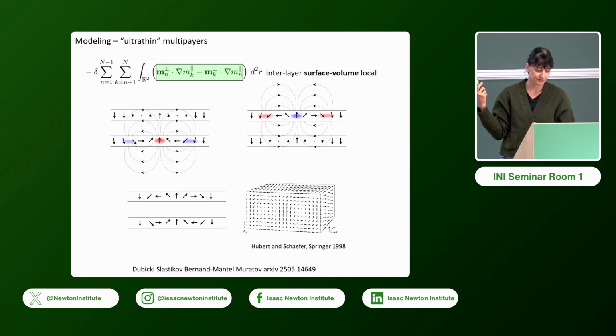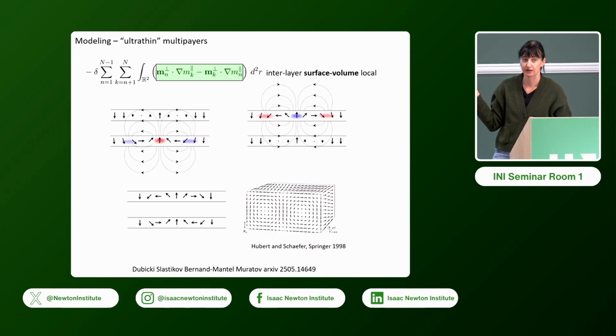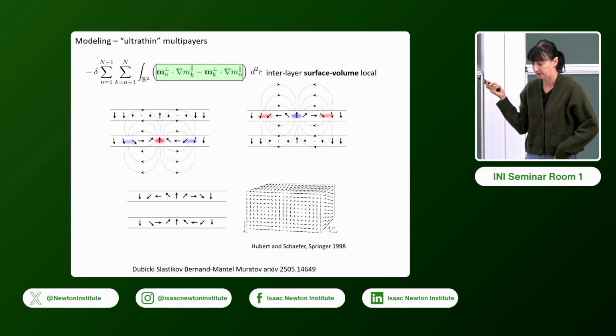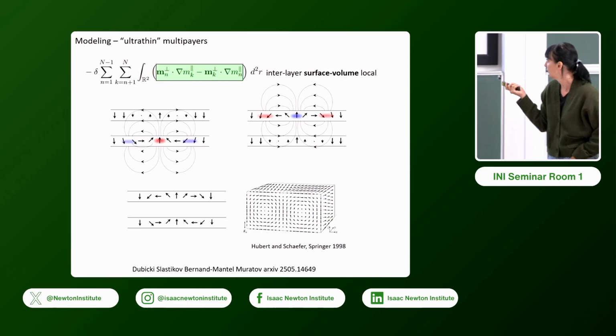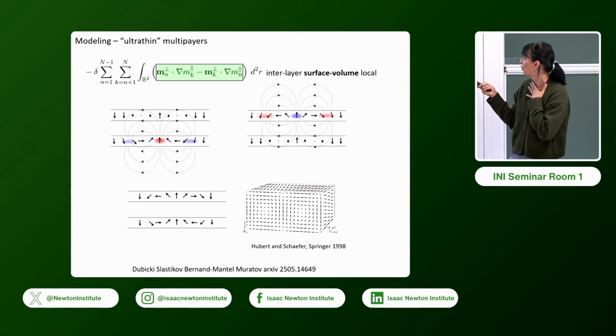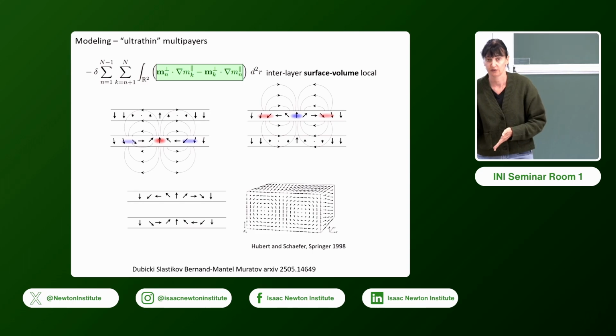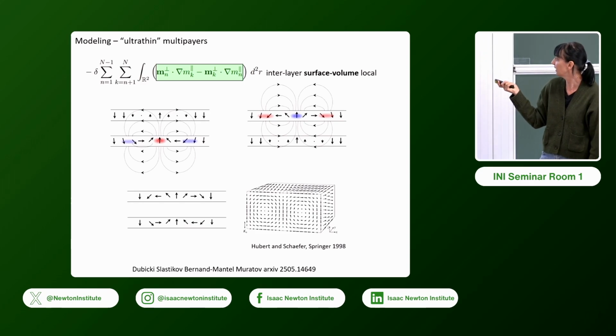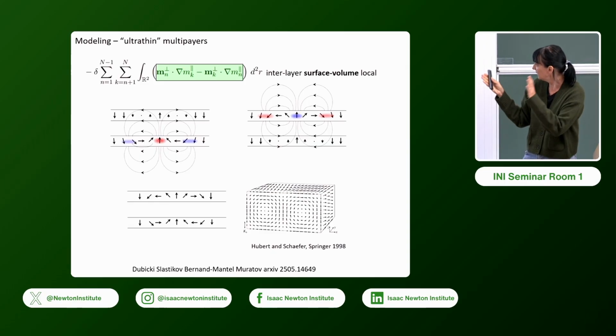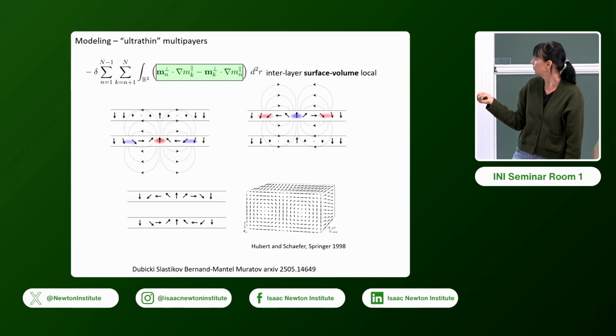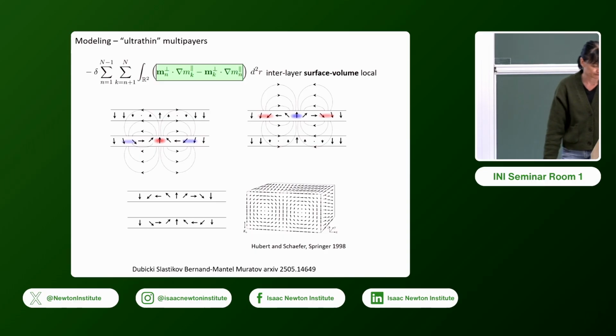And so we apply this to the case of a bilayer, and in this case we can prove, so this was done for the case of skyrmions, but this is the same idea if you have stripes or just a wall, that you have such a favoring configuration that is in fact reminiscent of flux closure that this stray field wants to obtain. So this is some sort of toy model where we recover flux closure, and here you can see two domain walls that are going to have this very chirality.